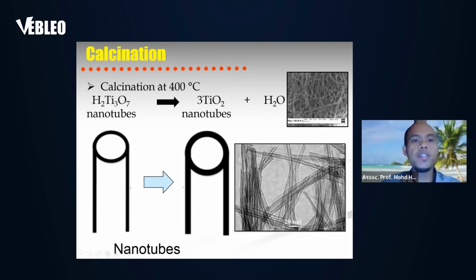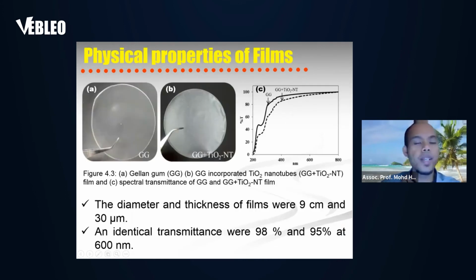Okay, so these are the physical properties of the film. This is the original GG film without the addition of titanium dioxide nanotubes. And here we have the GG plus titanium dioxide nanotubes film. The difference here is the physical form, and then we test using UV spectra. We can see the change in transmission rate.